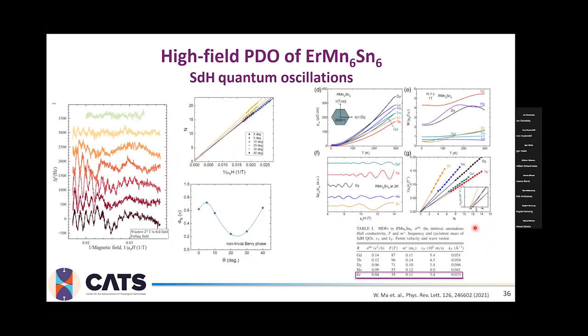Now, comparing with the data which were already reported earlier, the low field magnetoresistivity data showed that the erbium compound, which is here the orange curve, has a frequency around 35 Tesla, which is much lower than what we are able to see. So that means that we are most likely probing some different bands of the Fermi surface in that material.